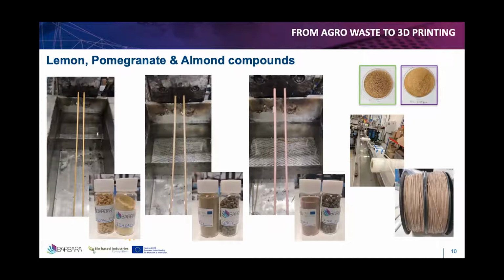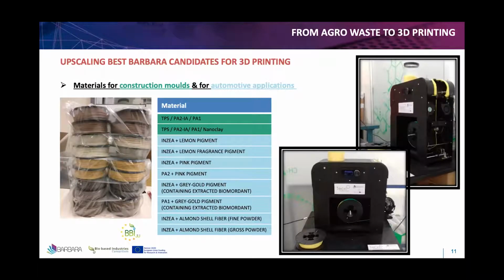In this slide, you can see examples of different materials and blends obtained through the piloting process. From the lemon peels, you can see also a gray and a pink color based on the pomegranate, and also some filaments coming from the almond shells. Here in this picture, you can see the production of the filament spools. Basically, we were using a pilot lab, small scale spooling machine, which has a small extruder that melts the formulation that we wanted to obtain, and we are able to get the filament with the adequate diameter and the adequate properties for the 3D printing technology afterwards.